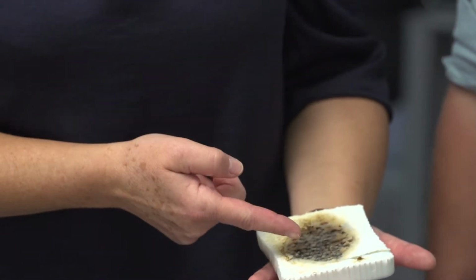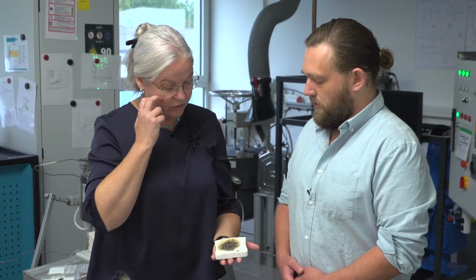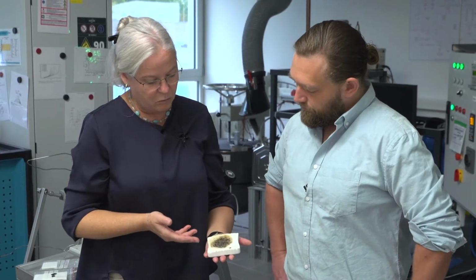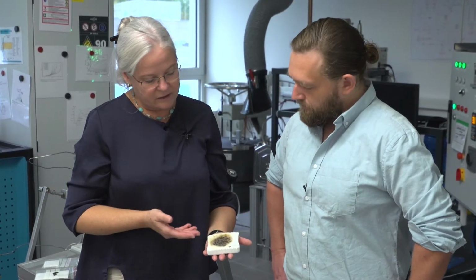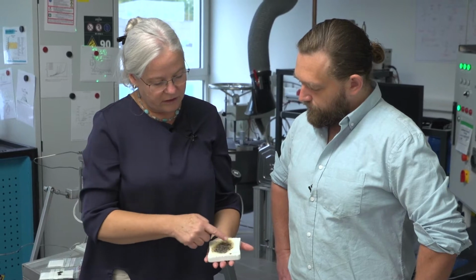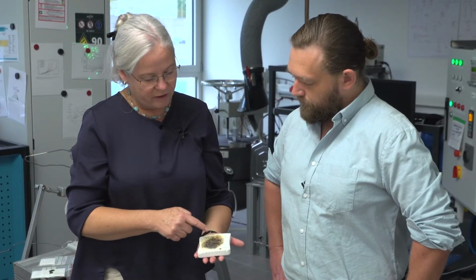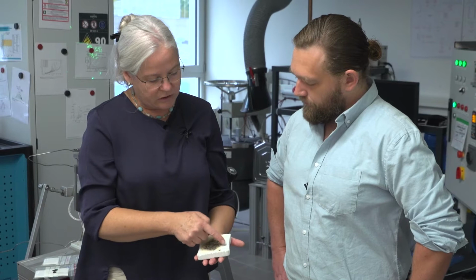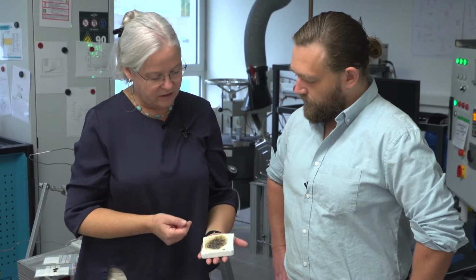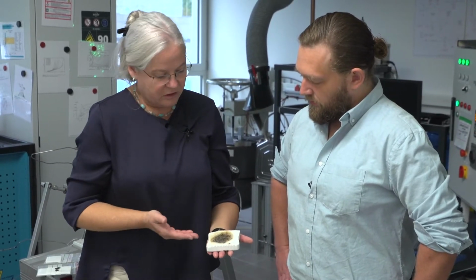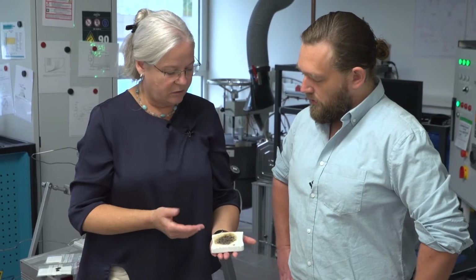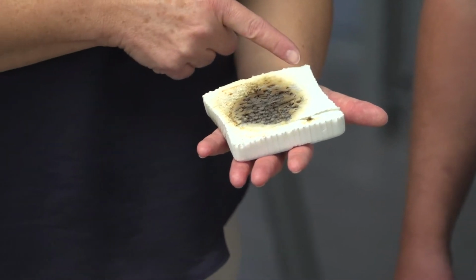Cool. And this fire test was done for several minutes. I would say this is more or less 10 minutes. And you can see that it is only affected in the range where the fire is coming. Wow. And outside it stays intact. It's amazing. So the tile itself stays intact too. It is only affected on the surface.